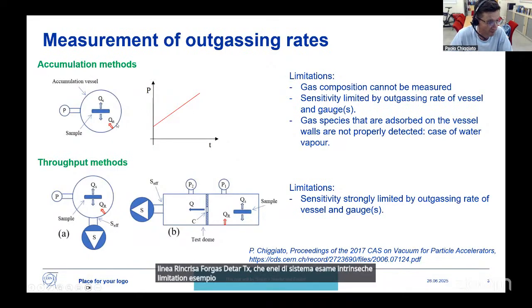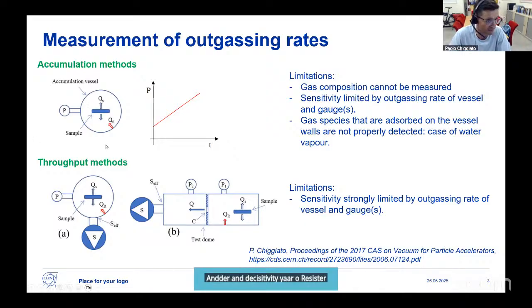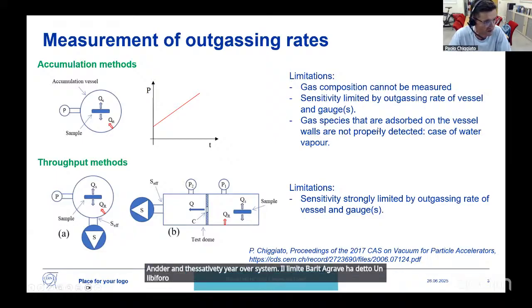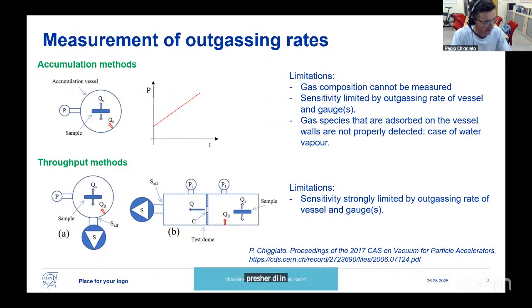For example, you cannot measure the composition of the gas, so you collect everything. The sensitivity of the system is limited by the outgassing rate of the vessel and also by the gauge. And as I told you before, if you have a species like water vapor, which is very interesting to measure in terms of outgassing, you cannot measure it because there is a continuous pumping. So you attain an equilibrium pressure between what is released and what is adsorbed.